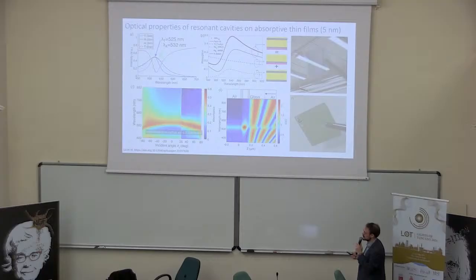You can excite this mode more or less at any angle of incidence. It's completely flat. And if you take a look at the electric field confined in this structure, you are coming from here with air, then the glass substrate, you go through the structure and then go out in air, so you can see where we are. The light that is coming is completely reflected up to the wavelength that is matched with this one. Then it passes and it resonates in the cavity, and then is reflected back. So what you get is a structure that is partially transparent, and it reflects in the opposite color, of course.